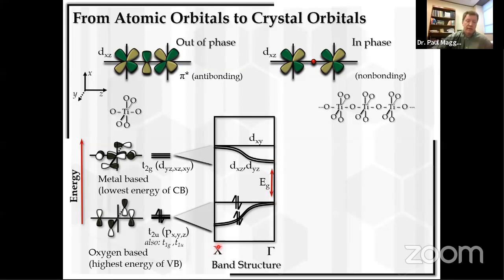And so as we go from X to gamma in the band structure, the d_xz and the d_yz run down in energy. And this dispersion is very important. When you have an electronic structure like this, which shows a large band dispersion, that leads to high mobility of carriers in that direction of the crystalline structure. So it's really important that you see this band dispersion, and have a high band dispersion if you're going to have a high carrier mobility in your material, so that they can reach the surfaces and drive that catalytic reaction before they recombine with the opposite carrier charge.